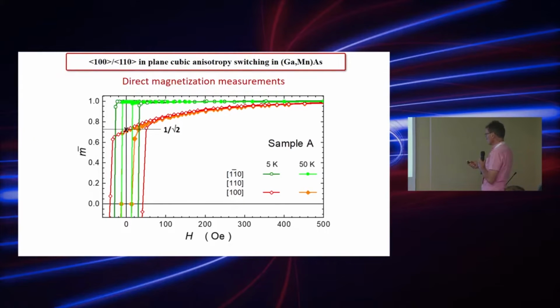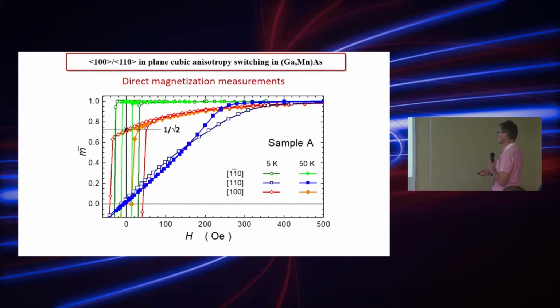Okay, so if this orientation didn't show us anything, we switch to the 110 orientation, and now there is a change. In these two temperatures we see two kinds of character of this magnetization curve. There is a concave curvature here and a convex curvature over there. So at high temperature we've got convex, and at low temperature we've got concave curvature. The question is, is it what we really wanted, or is it something else?